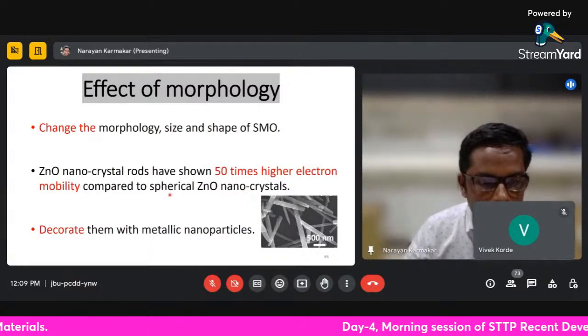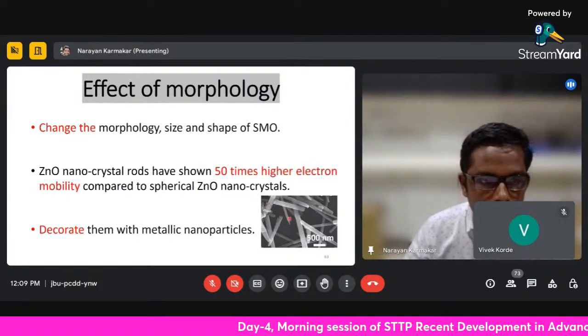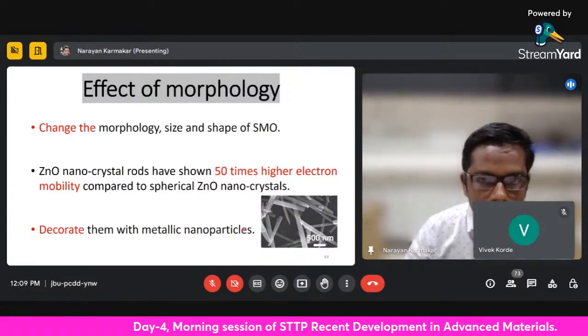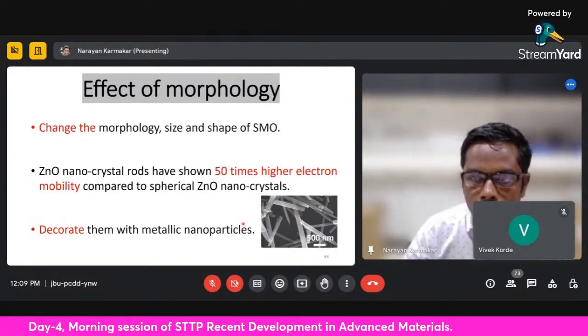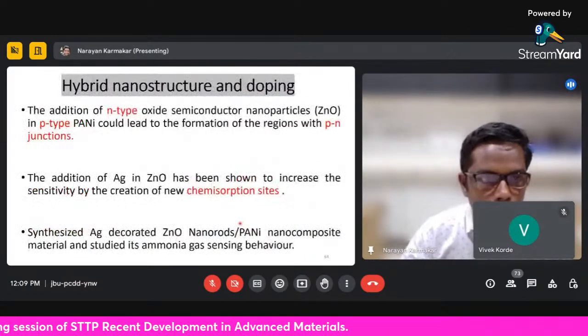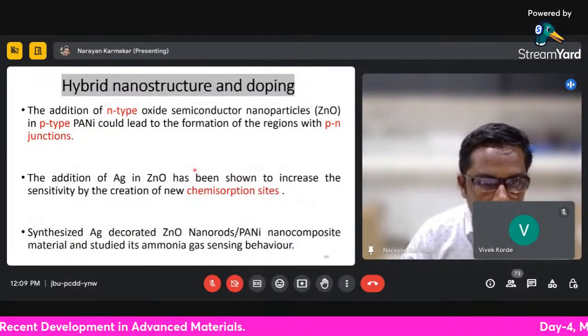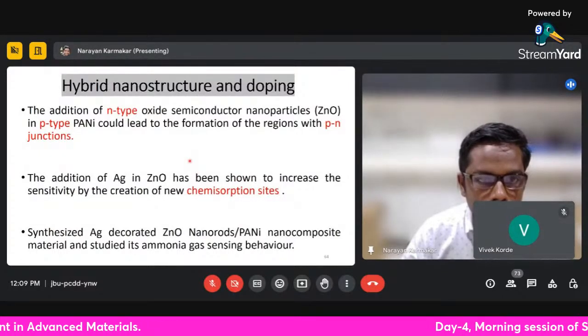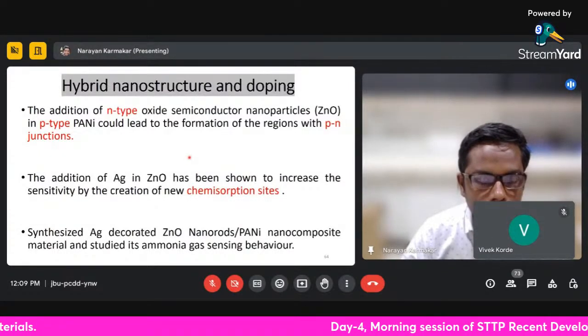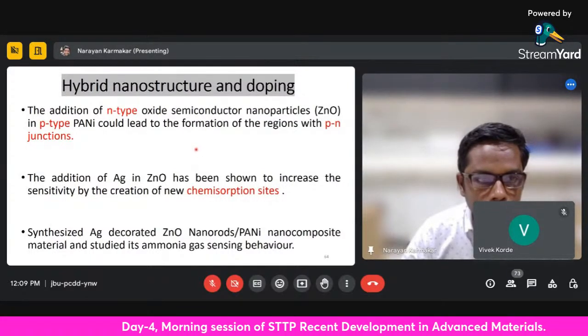After that, what we did is we synthesized first the zinc oxide nanorods, then we decorated them with a metal nanoparticle. So what you're doing is creating the hybrid nanostructure of the metal oxides and the nanocomposite, and then we decorate with the metal nanoparticle.